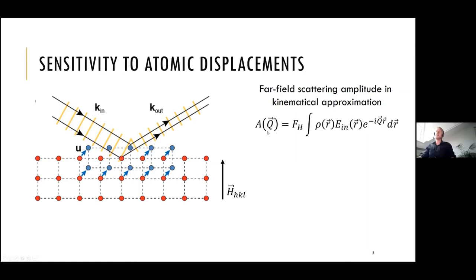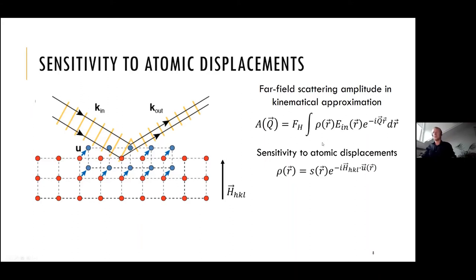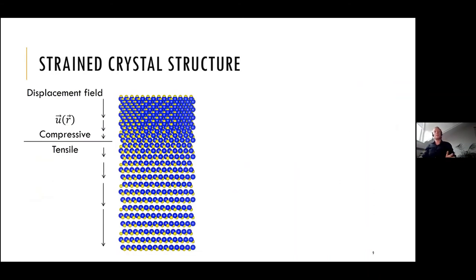By writing up, again in the kinematical approximation, the far-field scattering amplitude, we can see that in the case of Bragg scattering, we become sensitive to the deformations inside the crystal, which are located in the phase of the complex-valued object function. The S here is the shape of the object; since it's smaller than the coherence volume, it describes the morphology, and the phase is now our new deformation. By reconstructing the phase of the object, we can extract the displacement field, so how atoms are displaced from their position. By measuring a certain HKL reflection, because a crystal has different reflections, we access only a projection onto this direction. The strain in the crystal structure can be compressive or tensile, so this deformation describes how the structure actually looks.